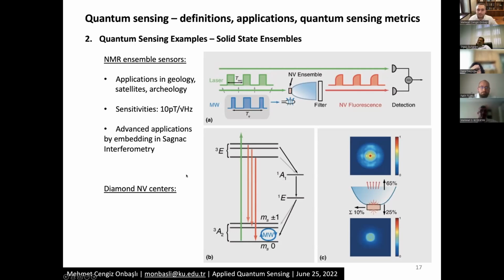But the idea is that these are the given energy levels: the triplet levels, and the singlet levels, which are the dark transitions. When I apply a green laser, I excite my electrons first. The ways our electrons can relax are either through the singlet states, which are dark, so we don't get their optical emission, or through the red emission. The red emission can fall back to either the ms equals 0 or ms equals plus or minus 1 states.